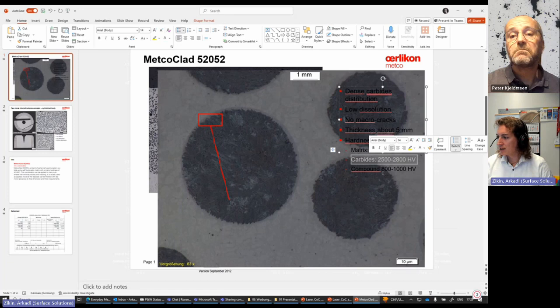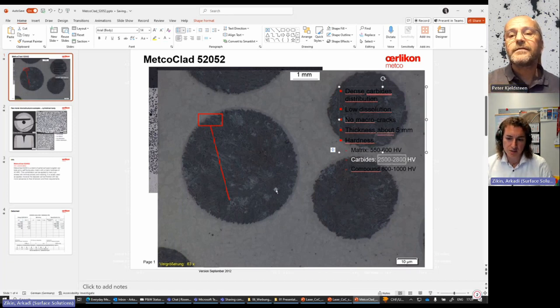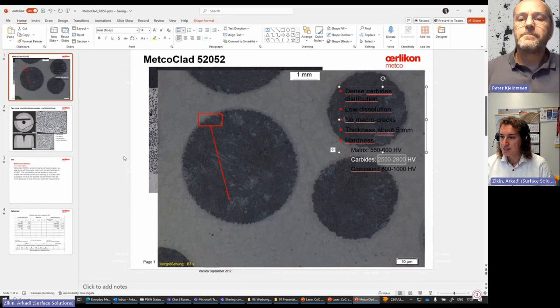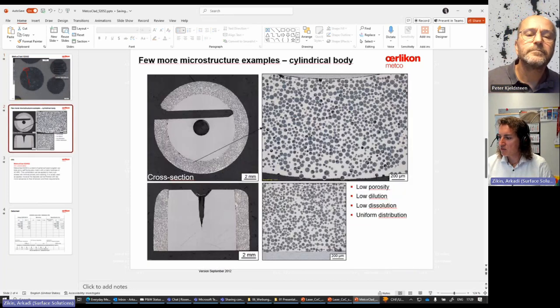I will put it now in white color so you can see it, almost up to 3000 Vickers. It's an impressive number. And if we look deeper, the carbides are extremely well and uniformly distributed within your coating profile. And this is only 60 weight%, which corresponds to 40 volume% of tungsten carbide within the metallic matrix. It is not possible to see on the microstructure that it is deposited. It has a casting microstructure, a typical casting microstructure.